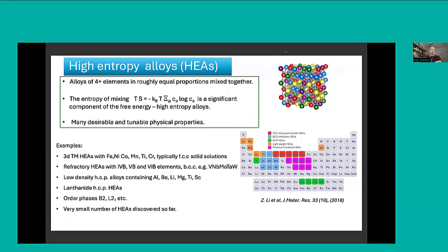Okay, and so I'm going to illustrate this with remarks on high entropy alloys. So these are alloys of three, four plus elements, and the thing about them is that the elements are mixed together in roughly equal proportions. And so this leads to the entropy of mixing being a really significant component of the free energy, hence the name. And that enables that if the appropriate elements do mix together, then they can form these solid solution phases,